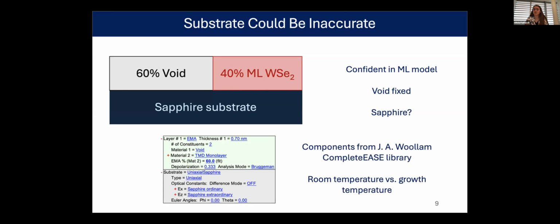So what's going on with the sapphire? Could that be something that's going on? Sapphire is an anisotropic material. That's how we treat our wafers. And so I was using this uniaxial type model in the software in that gray box where you can put tabulated files for the ordinary and extraordinary sapphire from the software library. And that is assuming a perfectly transparent sapphire, and the data comes from sapphire at room temperature, which again, we're at 1,000 degrees Celsius and it's a pretty intense environment in there. There's some other things going on.